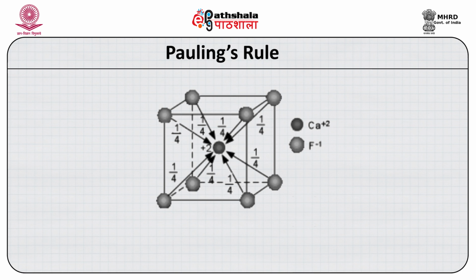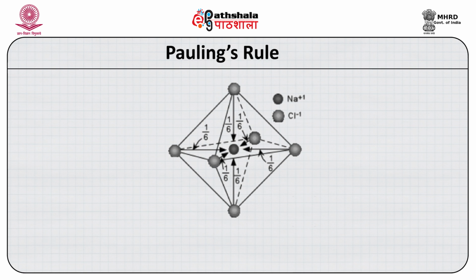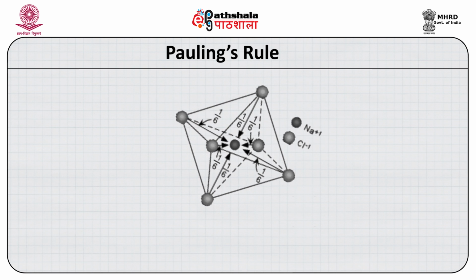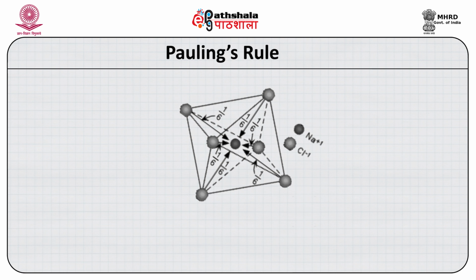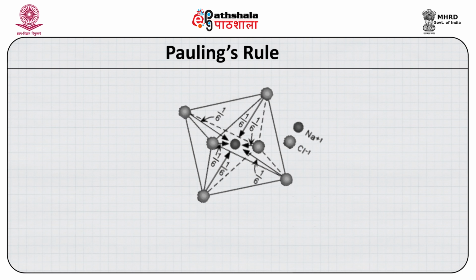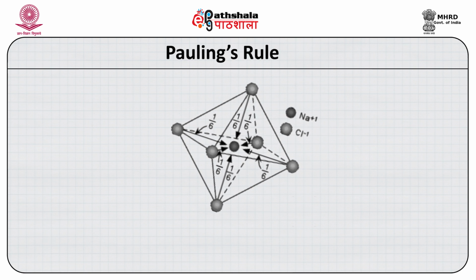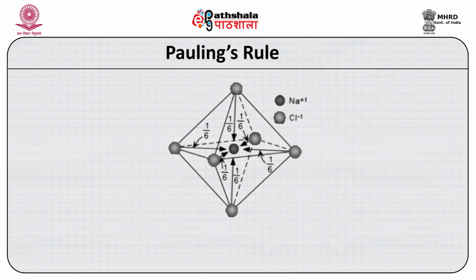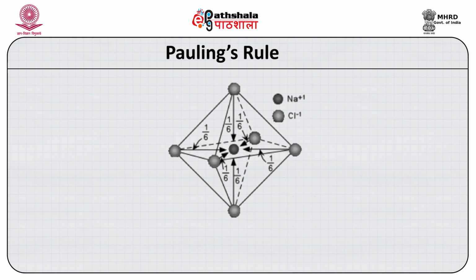In case of NaCl, each positively charged sodium ion is surrounded by 6 chlorine ions with the singular negative charge. In the octahedral coordination, the coordination number is 6 and the charge is 1, so it works out to be 1 by 6. The strength of the negative charge which actually affects the Na ion is 1 by 6. Hence, one positive charge is balanced by the 1/6 negative charge of 6 Cl ions. If we multiply 6 by 1 by 6, it works out to 1.